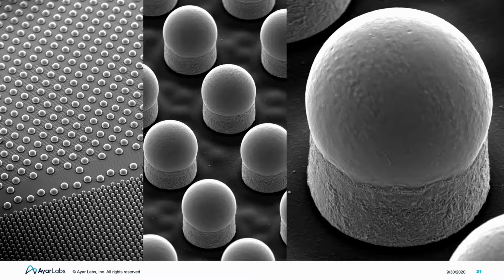Additionally, when plating either for the underbump metallization or the copper pillar itself, one must not contaminate the V-grooves or the spot size converter. Metals will cause a very high absorption and will severely impact the performance of the fiber attach process. Therefore, it is an opportunity for materials and process development to create high-volume manufacturable copper pillars on V-groove-enabled silicon photonic wafers.